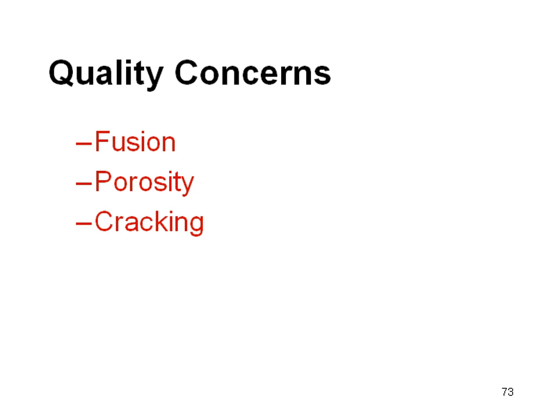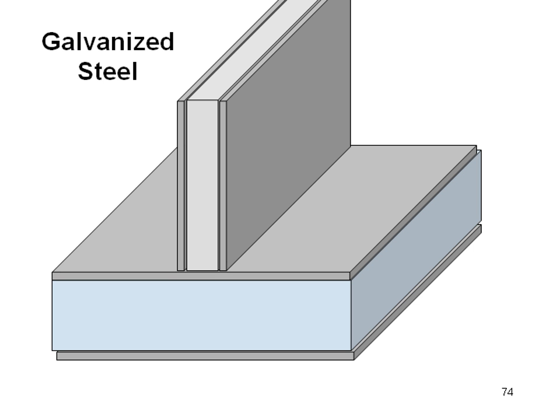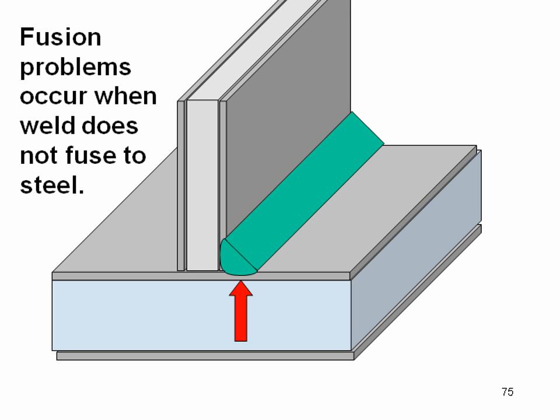Now, this illustration is trying to show a piece of galvanized steel, and I've tried to use different colors to show that the virgin steel is underneath this coating of galvanized. And when I go to make a weld, it is possible on a very heavy galvanized part to fuse the weld metal to the galvanized, but for the weld to actually not fuse to the steel. Now, if that's the case, the strength of the connection is dependent on the strength of the galvanized coating. And that's not what you want to do for the design of your elements. That's not what we've assumed. So you have very little strength if you're not penetrating through the galvanized coating.